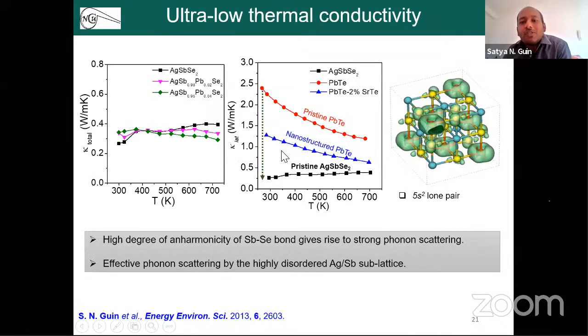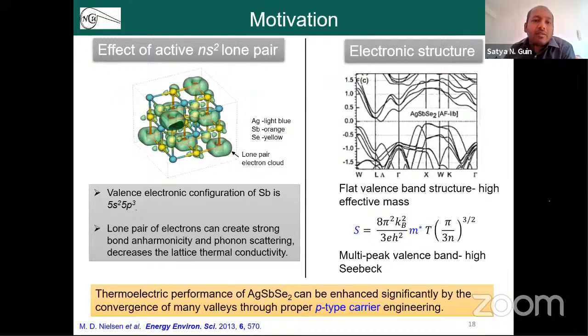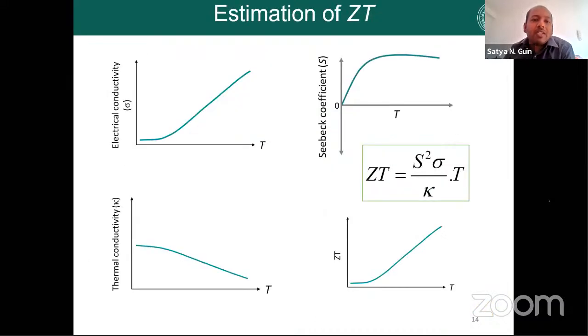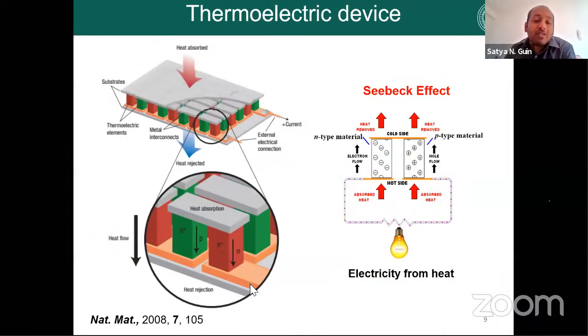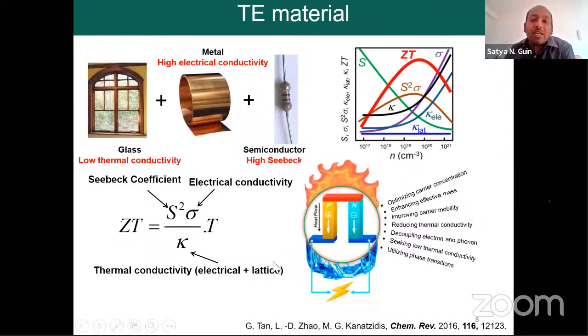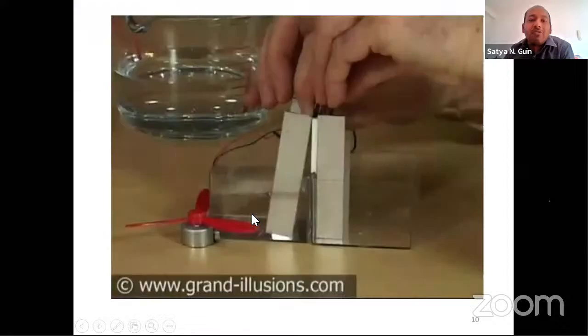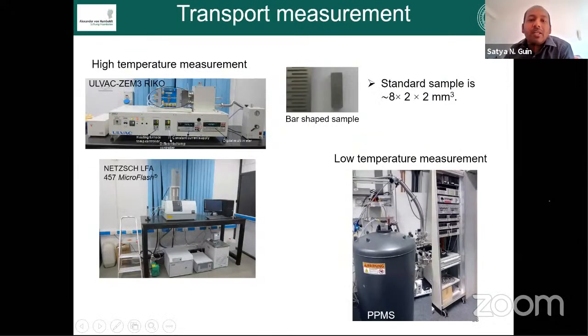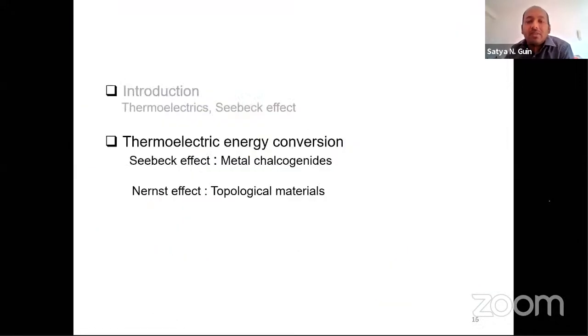So thermal conductivity, basically, if you have a system, in principle it can be 0, but it is not possible to achieve. You always have a lattice thermal conductivity which is contributed by the phonons. I can say till now in the literature, people have seen values like 0.3 or 0.4.